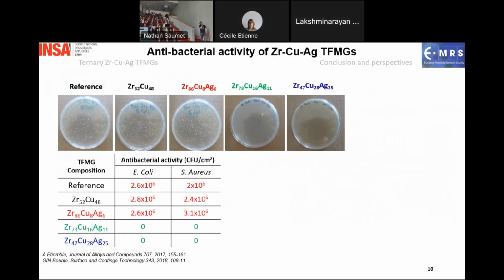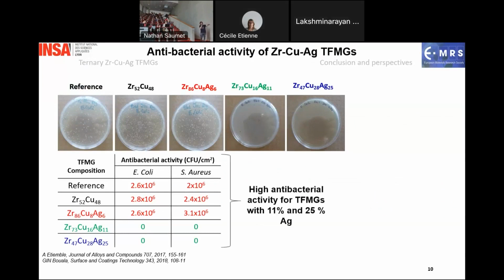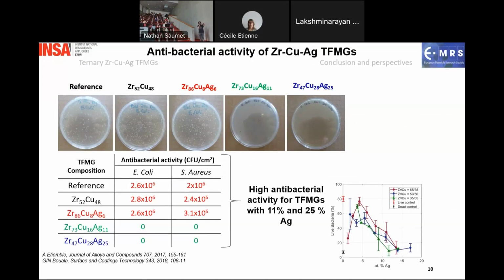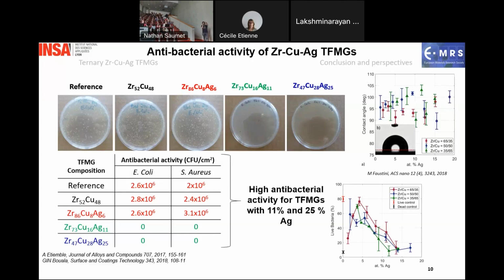By checking the biological properties, we saw that the antibacterial activity for E. coli and Staphylococcus aureus shows that at 11% and 25% of silver, we kill all the bacteria. We can also make a scan of the silver concentration, and here we have the live bacteria in percentage, and we see a rather linear shape. So by increasing the percentage of silver, we can change the bacteriological property of the thin film. We also checked that the wettability is not changed by changing the percentage of silver, so these bactericidal properties are only linked to the chemistry of the surface and not the wettability, just by adding more silver into the metallic glasses.